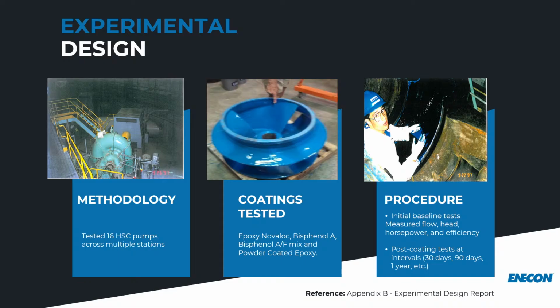So again, they were doing this over the long term. They did test some different systems on that, my company being one of those, and they did work with some other manufacturers on that as well. So we're an epoxy novolac manufacturer, but they did powder coat. They wanted to determine which ones were going to work out the best. And here's the procedure. They did baseline tests. They wanted to measure flow, head, horsepower, and efficiency. And then they wanted to do post-coating tests at intervals. So they did open that up, and they wanted to see how it looked after 30 days, 90 days, 1 year, etc. And what else did they do? I'll show you the next.